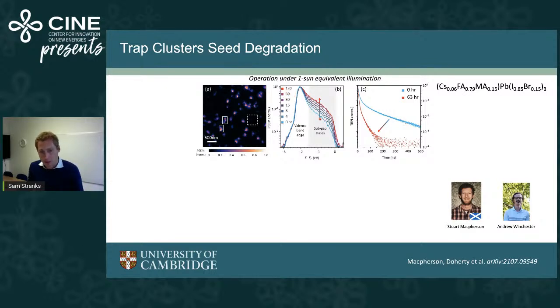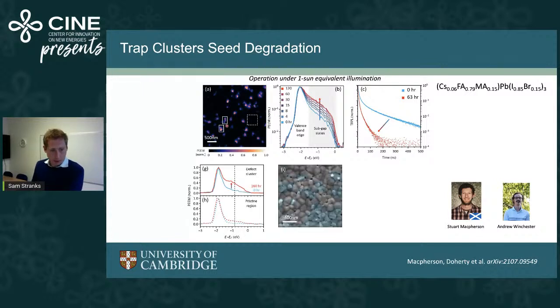And what we see is, as we illuminate, we see an increase in the subgap density of states. So we're starting to see degradation in these films. And we also see a quenching of the luminescence, which is also what we would expect with an increase in subgap densities of traps. That's spatially averaged across, but because we can spatially resolve these, we can look at a region that starts off as a trap cluster. So initially very trap rich, and that's shown in these two sites here.